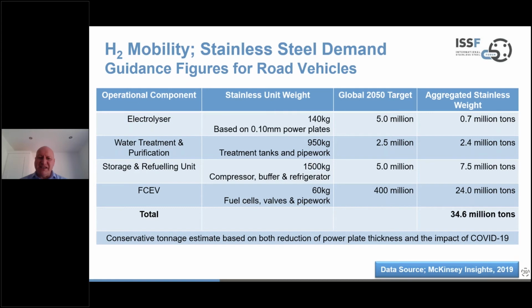Then what you're looking at is an electrolyzer needing about 140 kilograms of stainless steel based on the thin power plates, 0.1 millimeter. A water purification and treatment system requiring close on 1 ton of stainless steel. A storage and refueling unit, about 1.5 tons of stainless steel, and then a much smaller amount for the vehicles.